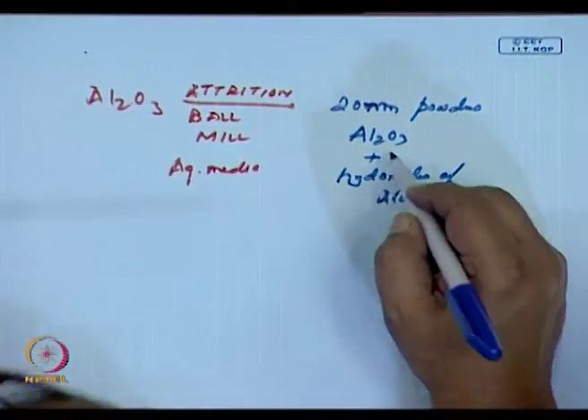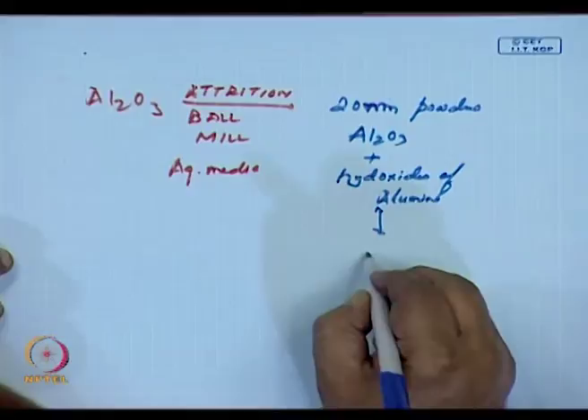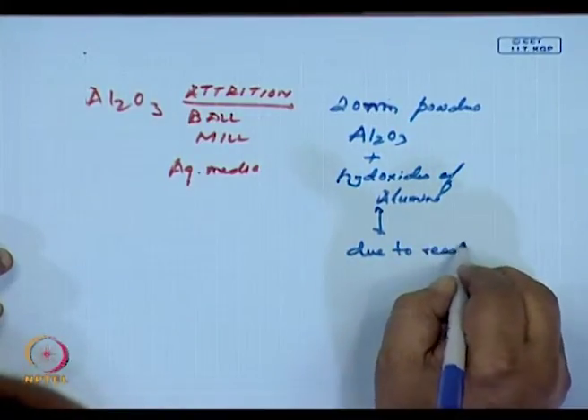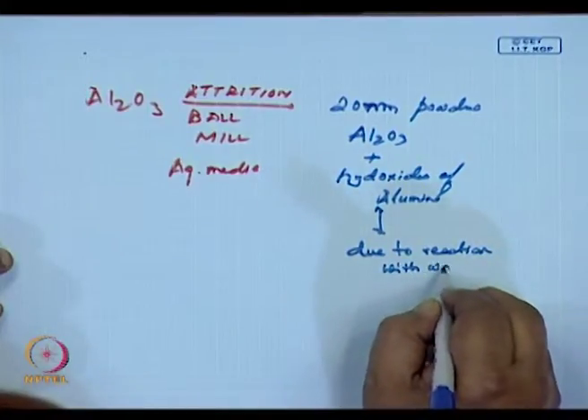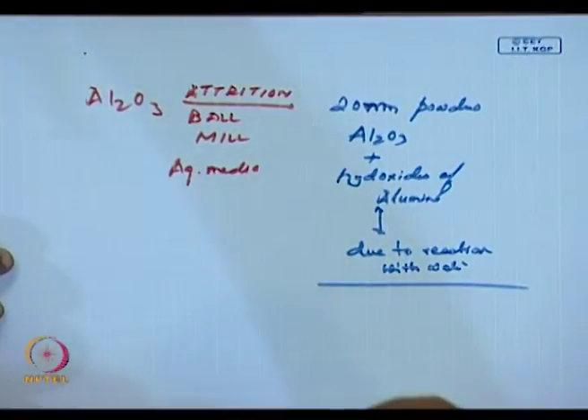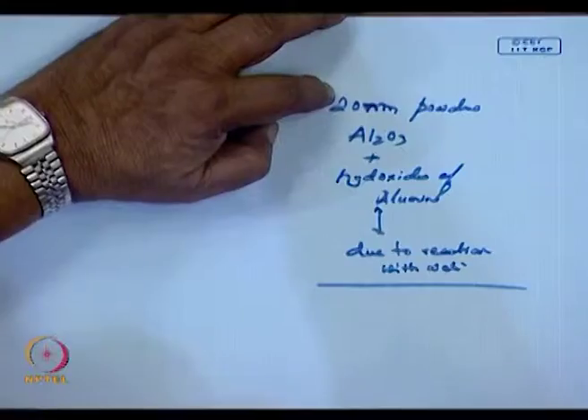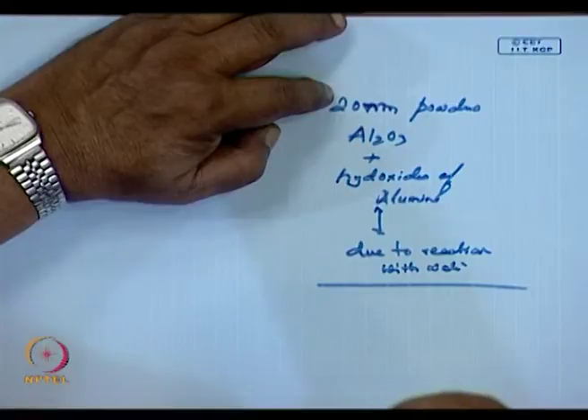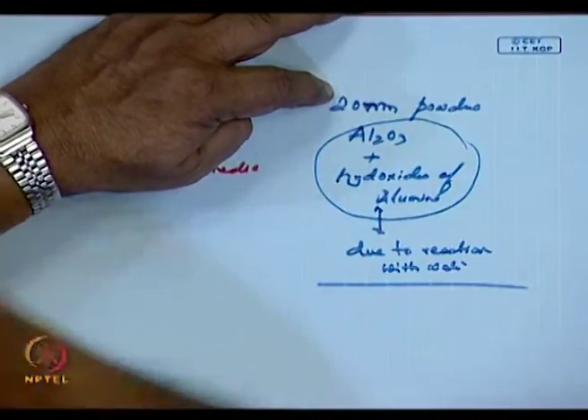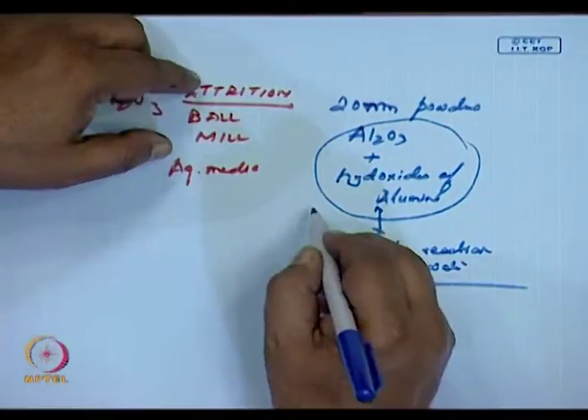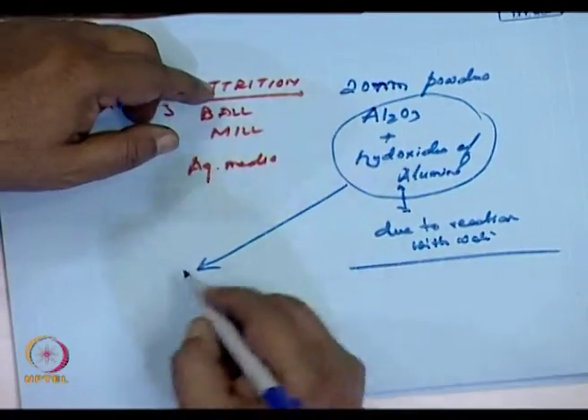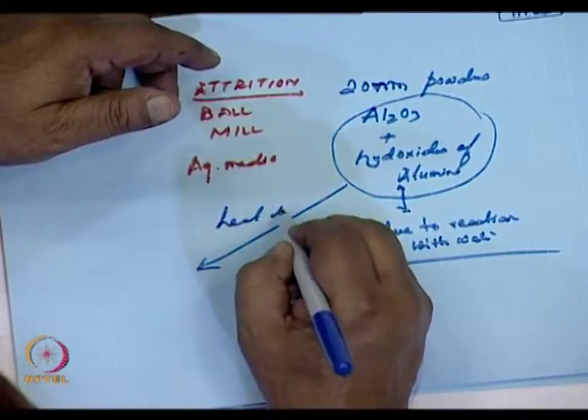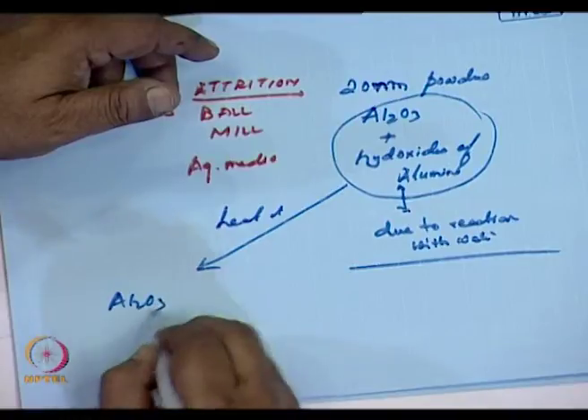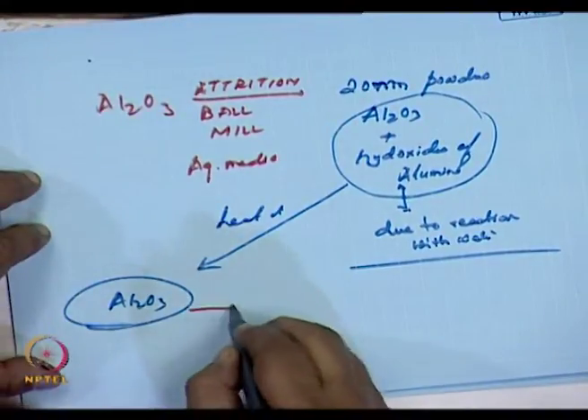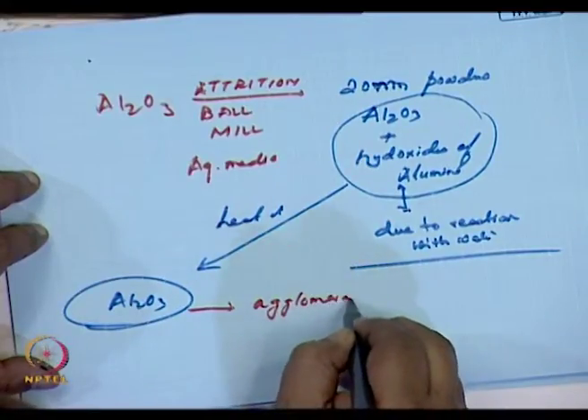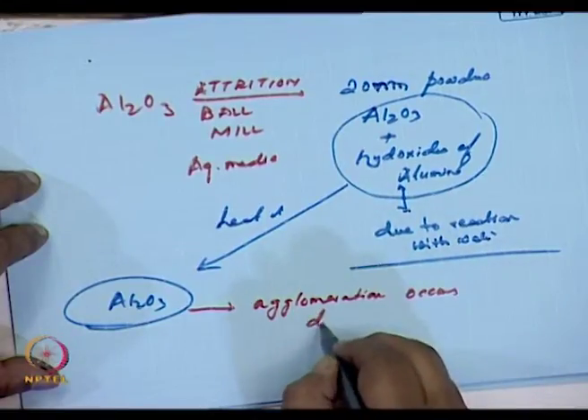Because as powder size reduction has occurred, the surface hydroxide is formed due to reaction with water. And hence, with attrition ball milling of alumina, we can get particle sizes down to 20 nanometers. I routinely get them, but I am hamstrung with the fact that it is a mixture. So this has to be processed again, and one of the easiest things is to heat it so that I get back alumina all over again. But then the problem is that agglomeration happens during heating.